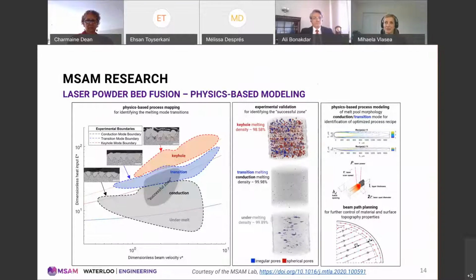In laser powder bed fusion, we are working with a very small laser beam spot. At this scale, materials can experience melting or even boiling and vaporization, depending on parameters used. Here we can see examples of how materials behave in boiling at the top, in transition or conduction with minimum defects in the middle, and in an undermelt condition as shown at the bottom in the CT scans of the objects shown. All these regions will have different mechanical properties and material properties.